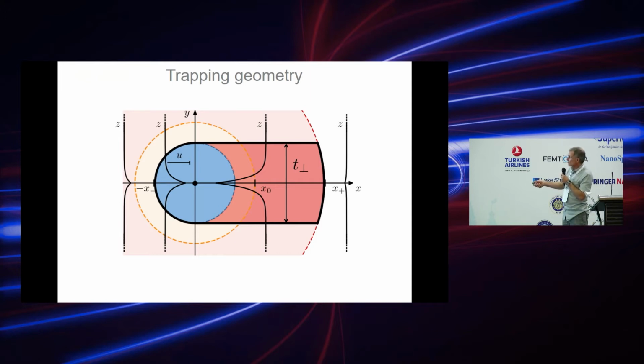Now, if we change this and view this axis not as Z along the vortex, but as Y in the transverse direction, we go to the transverse problem. If there is a head-on collision, the vortex goes straight onto the defect, then that's as I presented. Now, if it comes at some transverse distance, then it comes to this point and then jumps here and goes and jumps here, but it comes with some non-zero impact parameter.